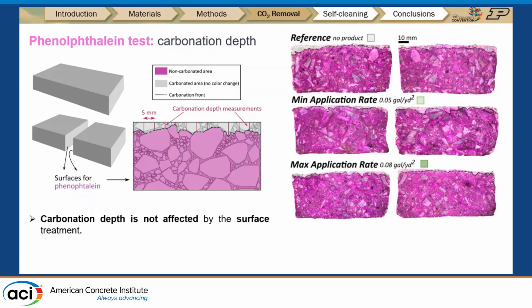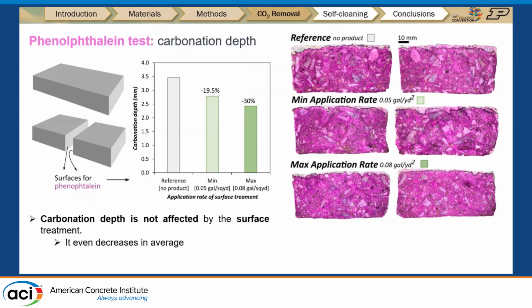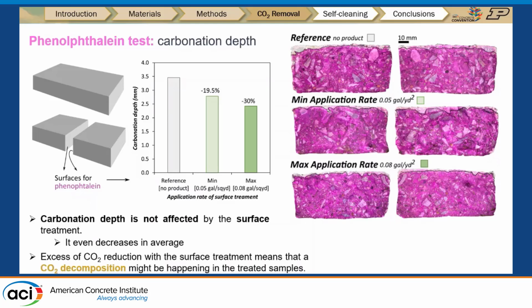If we look back at our phenolphthalein test data, we can even see that in the maximum application rate group, the carbonation depth even goes down. So the carbonation is slowing, it goes down, but we have seen more carbon dioxide reduction in our maximum application group. So the excess carbon dioxide reduction with the surface treatment means that there might be a carbon dioxide decomposition happening. So this is great because if it's decomposition, this might not be limited, and since the pH is increased, there might be no corrosion concerns. So one of the hypotheses we have is that this might be carbon dioxide photoreduction.